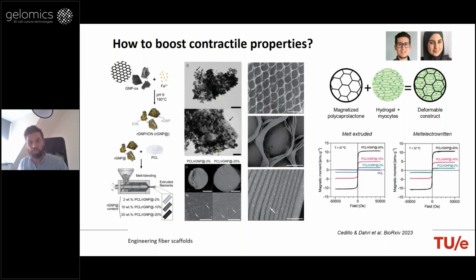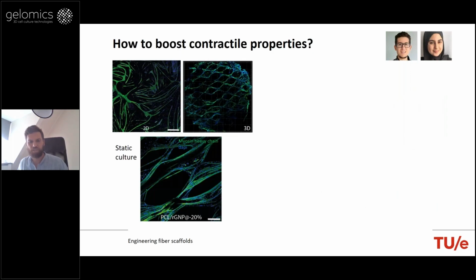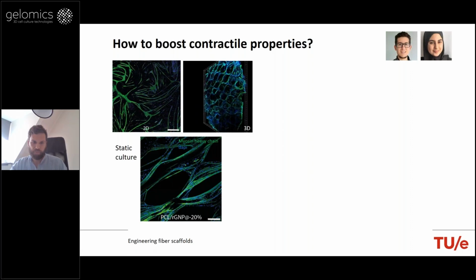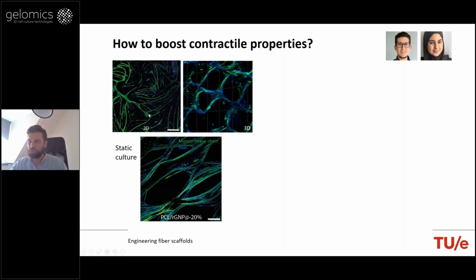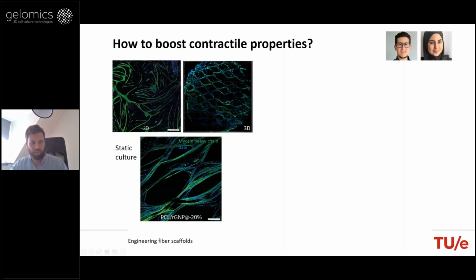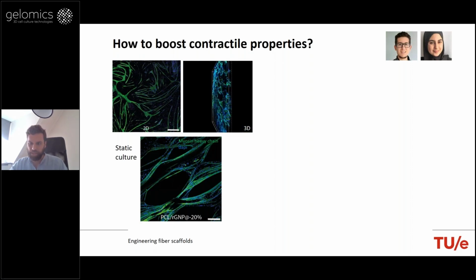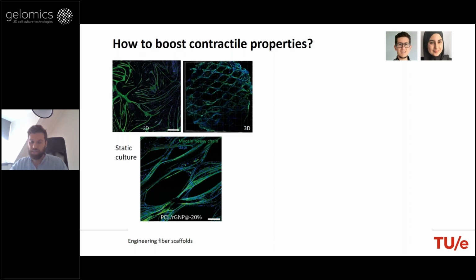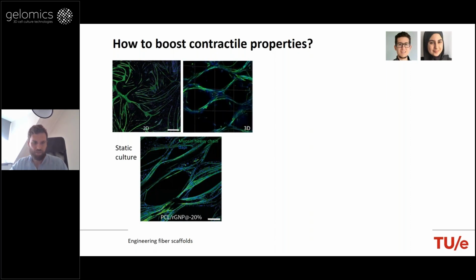The next step was looking at how the construct influenced cell organization. And here we took a cell line that was easier to work with. In this case, we looked at C2C12 myoblasts that we can culture on these printed constructs. What you can observe here is that the cells tended to align along the printed fibers, while that was not observed when the cells were cultured on a 2D platform or even on a differently shaped 3D electrowritten construct. We also looked at a myogenic differentiation marker, in this case MHC, stained here in green, and in blue the nucleus of the cells.